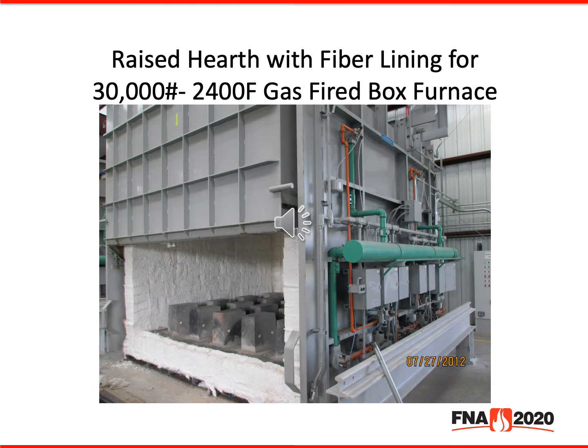In photograph 28, you'll see again this large gas-fired box furnace that we looked at earlier. Again, this is a direct gas-fired furnace with the ceramic lightweight fiber lining and a vertical lift door. This furnace was rated for 2400 degrees F for a 30,000-pound load. These again are for large castings and forging applications that are used for the aerospace and the oil field type market as well. These are direct flames, so the flames are typically sent between each one of these piers and fired opposite walls, so you get a good mixing of the gases and the temperature uniformity inside of the chamber.